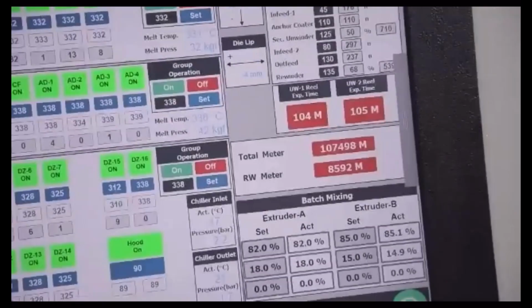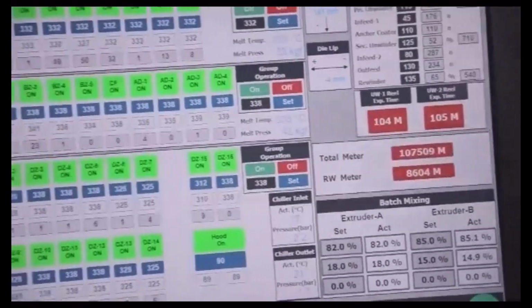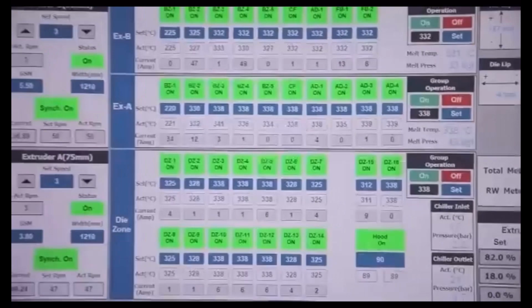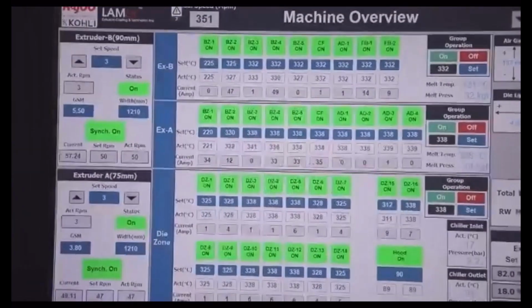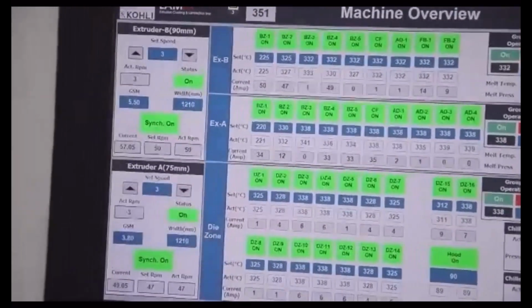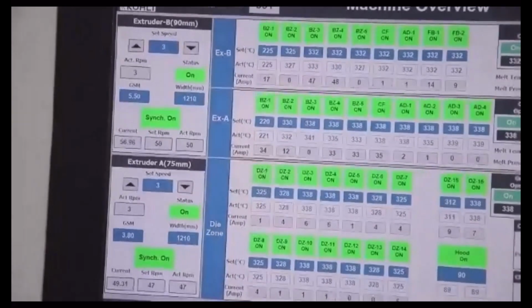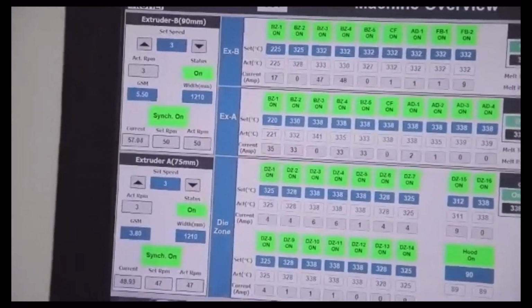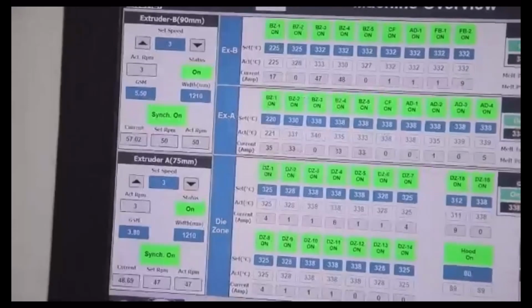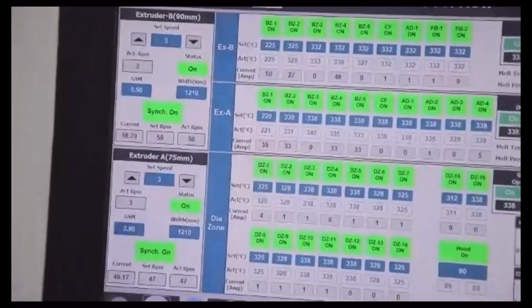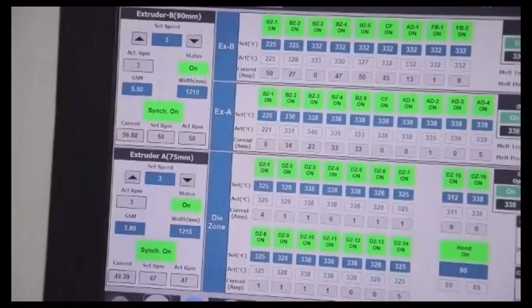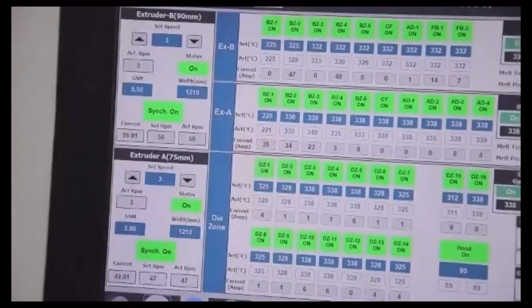The machine is currently running at, if I can see the screen, it was running at, oh, it's still running at 351 meters per minute. One can see the left panel where it shows the deposit by the extruders. The top one is a 90 mm extruder running at an RPM of 50. The bottom is a 75 mm extruder running at 47 RPM and depositing 3.8 GSM. So close to 9 GSM is being deposited.